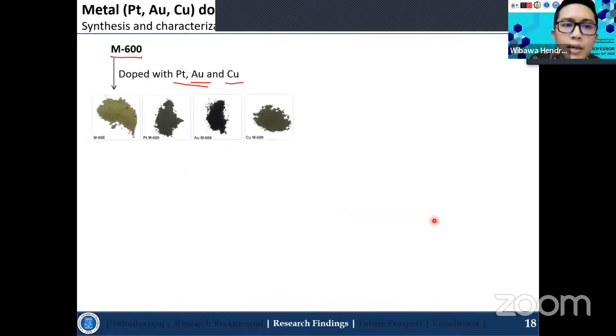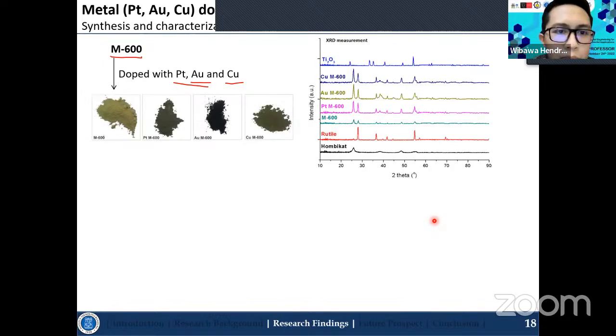And follow by the doping with several metals, because the mixtures of the composites of the TiO2 under 600 degrees Celsius calcination temperature give the most active catalyst for the methyl orange degradation, and I tried to dope with several metals to improve the efficiency of degrading the methyl orange compounds. So in these cases, I dope with platinum, gold, and copper.